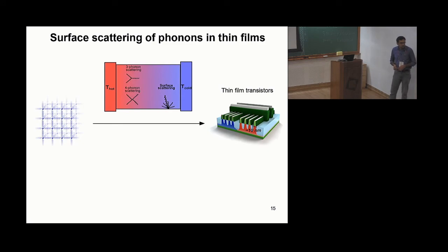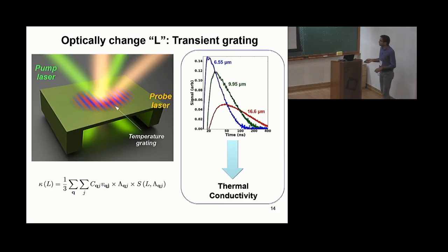Velocities you already know. The velocity and the heat capacity, for my work, I used calculated results, but you can do measurements of both sound velocity and heat capacity. The phonon dispersions you can independently measure, for example, via neutron scattering.